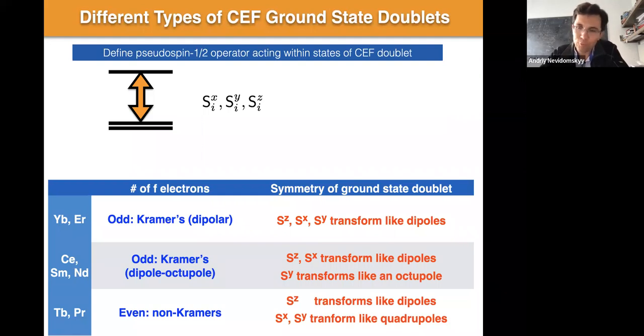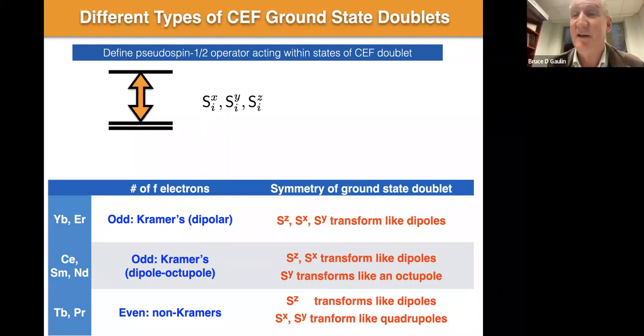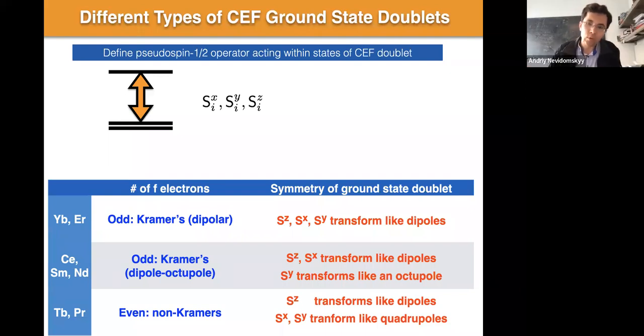But the statement coming from Roman, as I recall it, was that their measurement done on the HRPT machine, they have a better resolution at high Q. And the argument is something to do with the angle of the Bragg monochromator. You could see that I'm out of my depth here. No, you're actually correct. That's exactly the argument. So his argument was that when he takes his crystals and measures this on the WAND machine, however you pronounce it, he gets the same data that doesn't seem to have high Q data. And when he uses D20 or the HRPT machine, he gets the data that you showed from his Nature Physics paper.